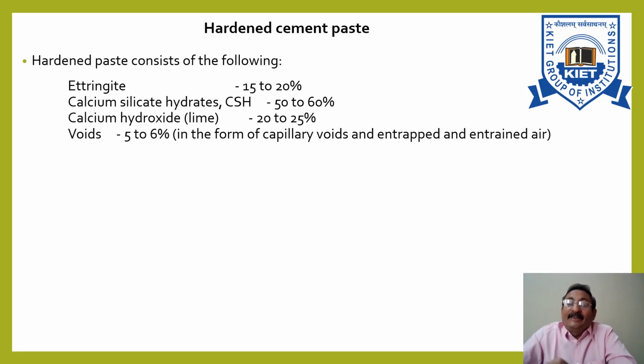Now, the increase in volume of gel due to complete hydration could fill up the space earlier occupied by water up to a water cement ratio of 0.6 or so.